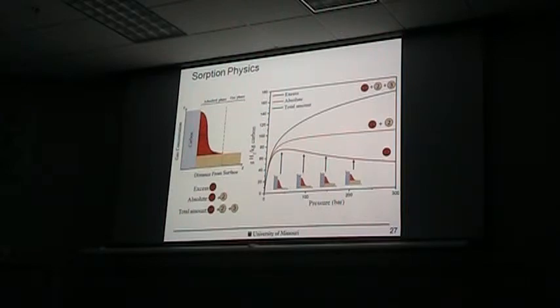And you see these different isotherms, you can plot them. This is excess, this is absolute, and this is total amount. The interesting point is if you look at this shape here, it rises and then starts dropping. This drop happens if the gas phase of your gas has the same density or higher density than your absorbed film. Then it starts leveling and dropping off here. So actually we use this drop here to calculate or to see what the density of our film is. So that's why we know that we have almost liquid density in this film.